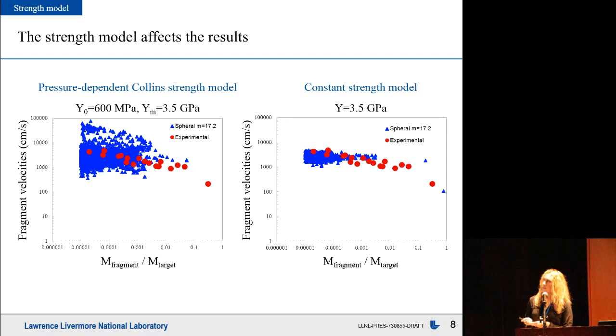But when we use the constant strength model, where the shear modulus and yield strength are fixed, this broad range of fragment velocity shrinks to become 1 trend line, matching the experimental trend line shown in red almost exactly. We didn't want to just stop here.